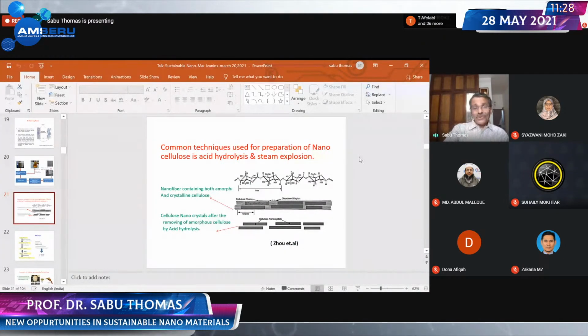I told you that if you use strong acid, you get short crystals, nanocrystals. If you use weak acid, light acid, you get long nanofibers. If you use a strong acid, what happens? The strong acid can kill all the amorphous part of nanocellulose, and you get short, pointed nanocrystals.